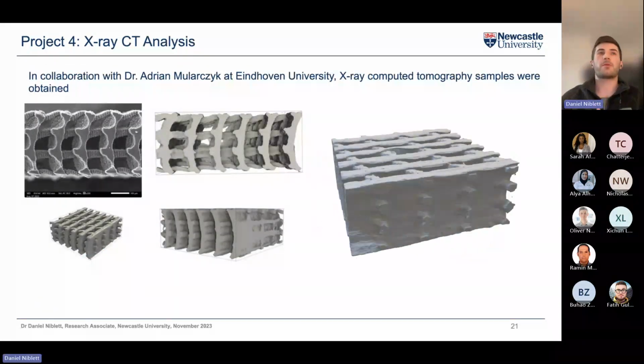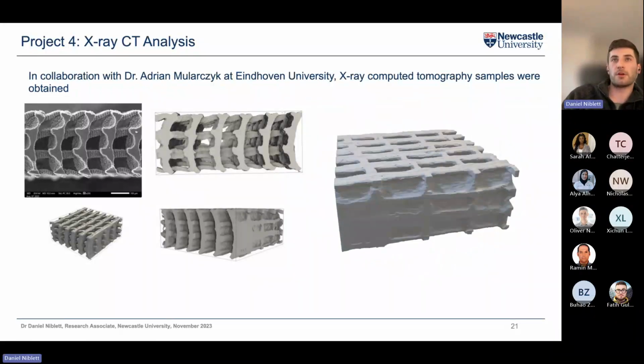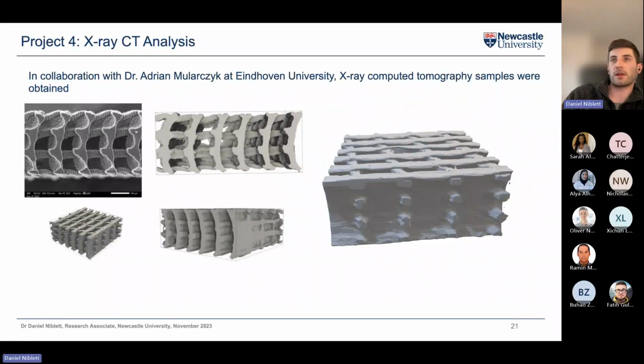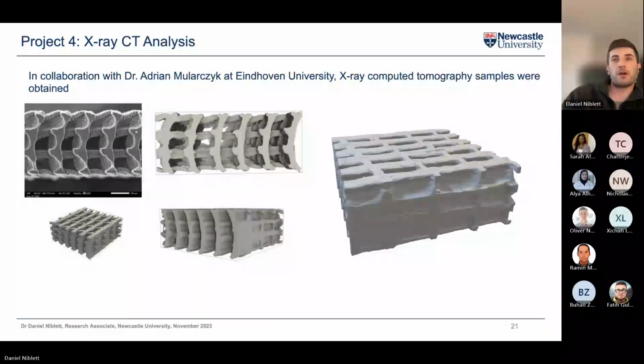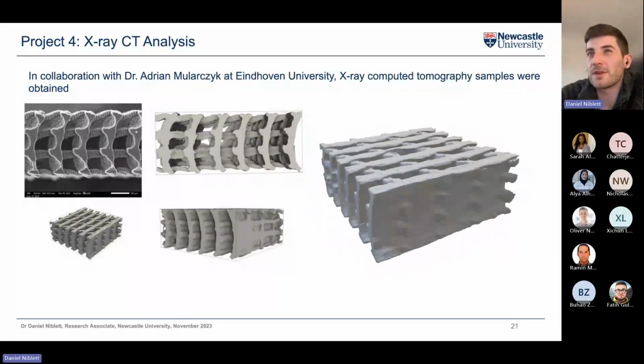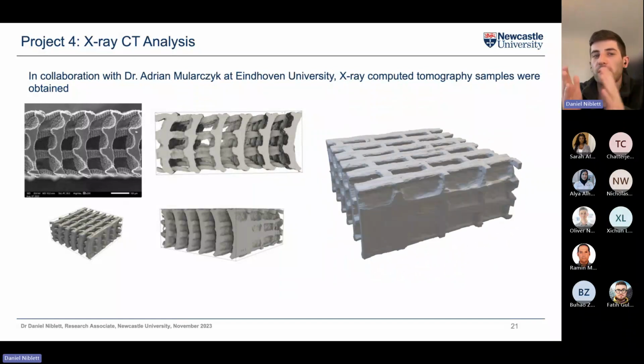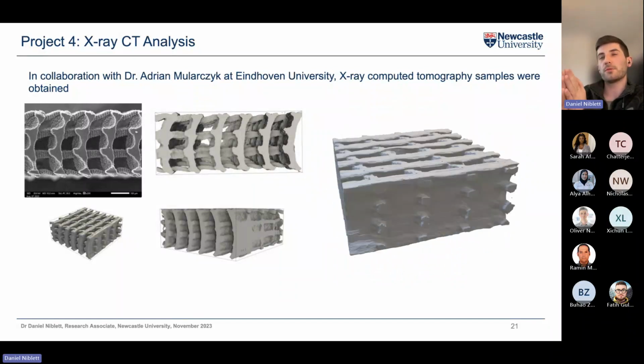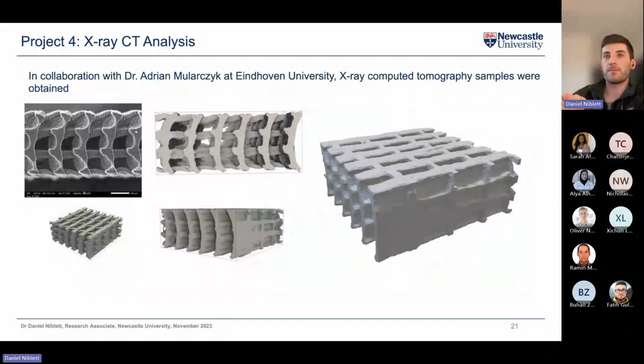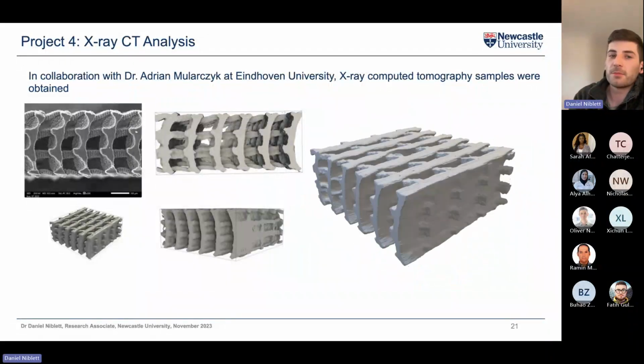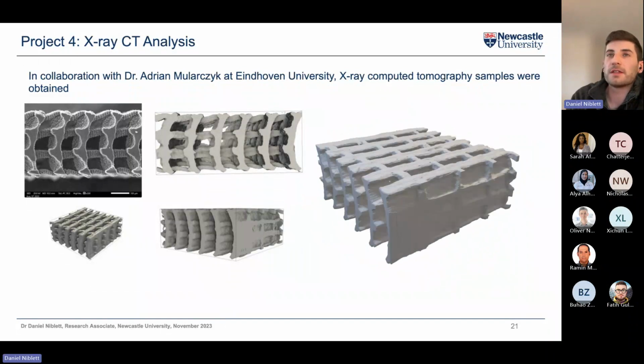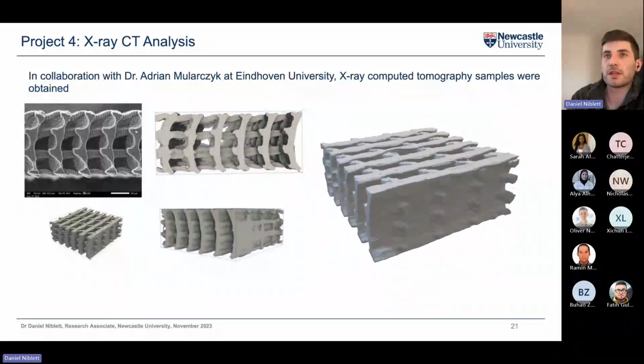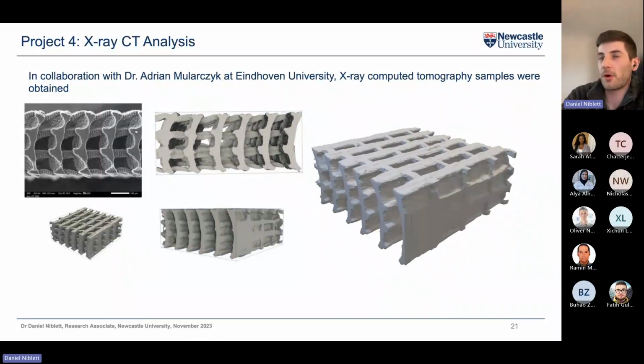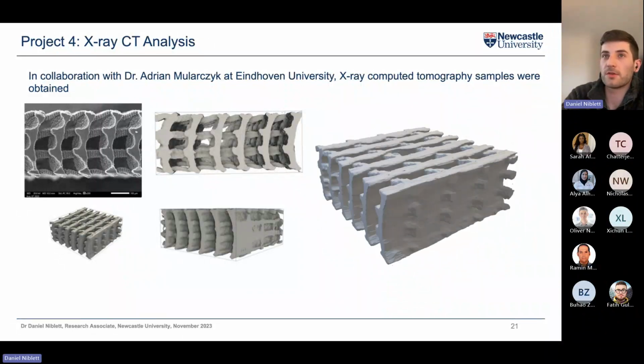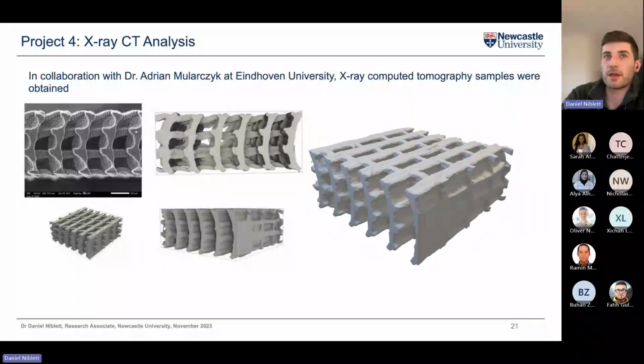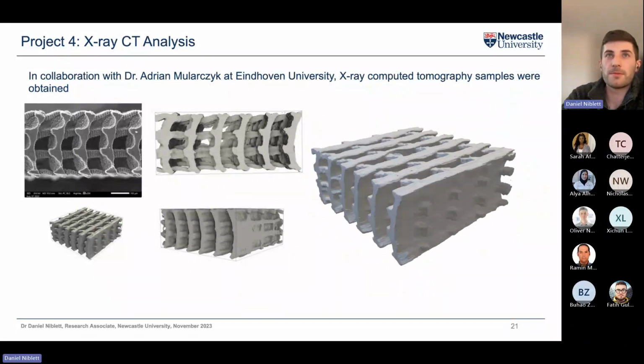And now in collaboration with Adrian from the Eindhoven University, we were able to get some X-ray computed tomography samples of this material. And what we actually found is there were some defects in the printing process, which introduced these parallel walls, which was to do with the orientation of the printing. But we didn't know that at the time before we got these X-ray CT samples quite late on in the project. We've since amended this problem and we've got a new material to use, but the results I'm showing here are generally with this type of material.